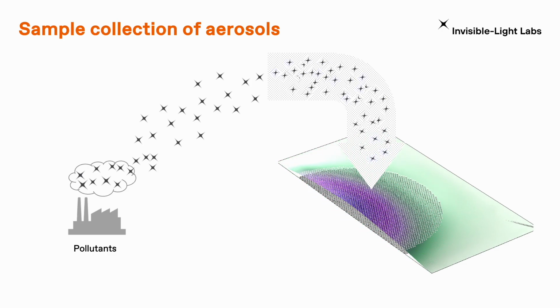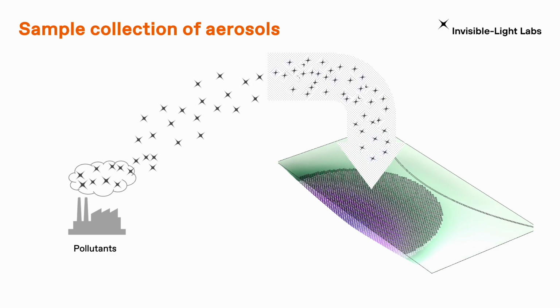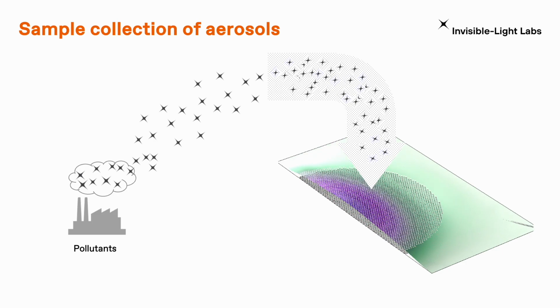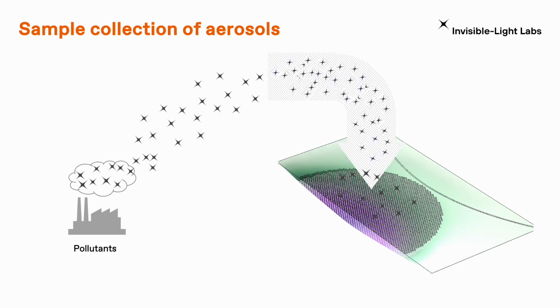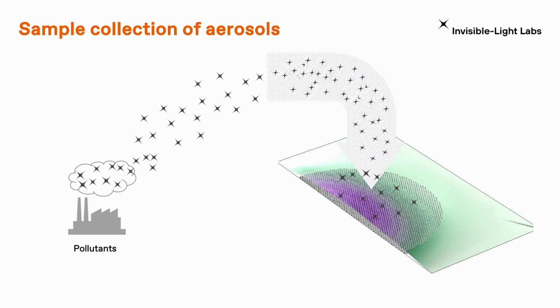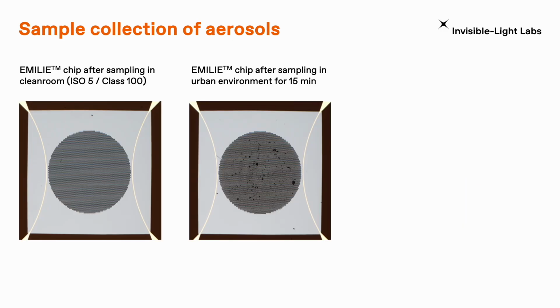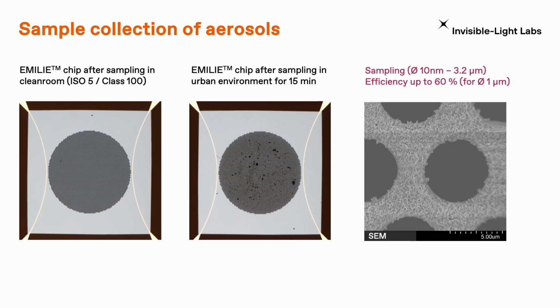As air accelerates through the perforation, particles as small as 10 nanometers deviate from the laminar streamline and are collected by impaction on the chip's surface. This impaction-based sampling technique enables the capture of particles as small as 10 nanometers directly from an aerosol, achieving an efficiency up to 60% for particles measuring 1 micrometer.